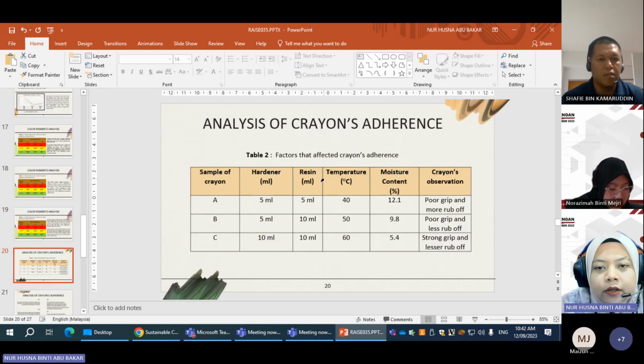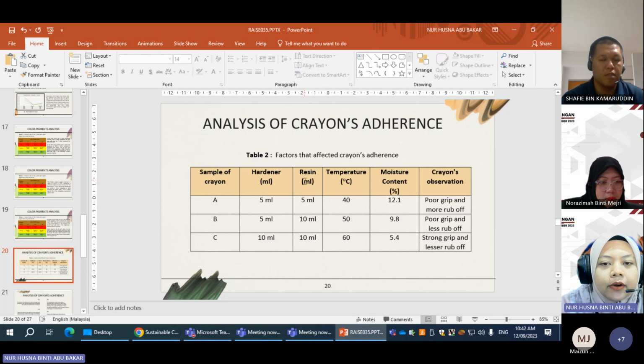So for the analysis of crayon adherence, we have several factors that affected it, which are the amount of hardener, the amount of resin added, the temperature we use, and the moisture content inside the sample. So this is the observation for the crayon. From this table, we can conclude that with adding 10 ml hardener and 10 ml resin, at 60 degrees Celsius, we have a strong grip and less rub off.